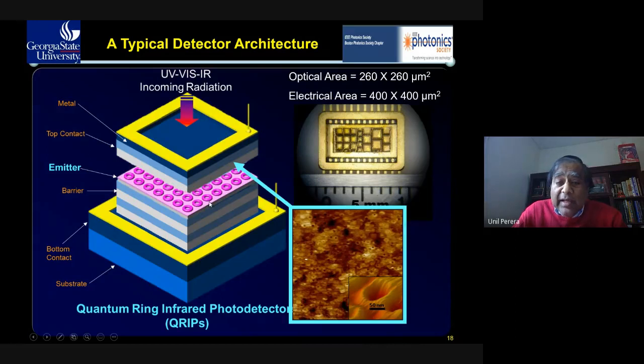And if you anneal the quantum dots, you can get what is called a quantum ring. And so this is a quantum ring. The reason for annealing is to get a quantum ring. Quantum dot is self-assembled, so there is not much control in quantum dot size. And the size of the dot matters to have the energy levels. So the energy levels cannot be adjusted easily in a quantum dot.